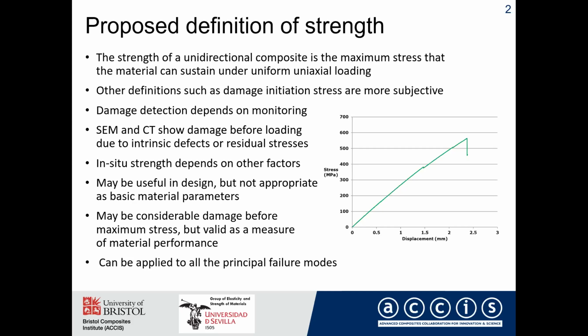All these definitions may be useful, in particular in design, but the question is, are they appropriate as basic material parameters? And we argue that really we should go with this maximum stress as the most meaningful strength parameter. Now, there may be considerable damage before you reach the maximum stress. And in the case of this one I've just shown on that stress strain curve, there was large scale delamination. But nevertheless, I think this is valid as a measure of the ultimate material performance. And of course, this can be applied to all the principal failure modes.